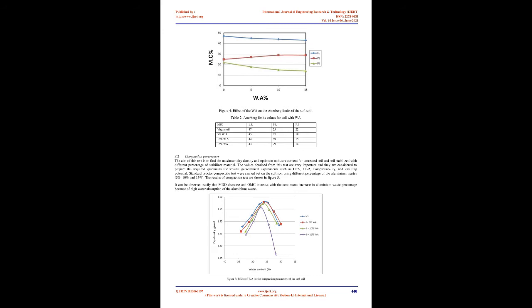Standard Proctor compaction tests were carried out on the soft soil using different percentages of the aluminium wastes: 5%, 10%, and 15%. The results of the compaction test are shown in Figure 5. It can be observed easily that MDD decreases and OMC increases with a continuous increase in aluminium waste percentage because of the high water absorption of the aluminium waste. Figure 5: Effect of WA on the compaction parameters of the soft soil.